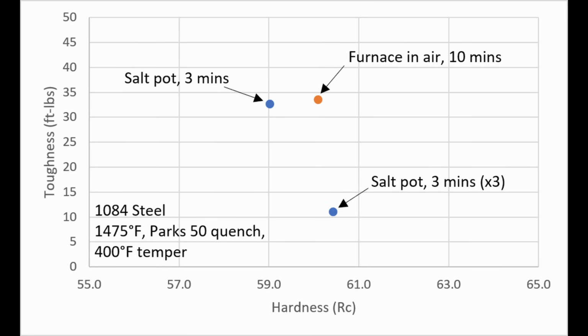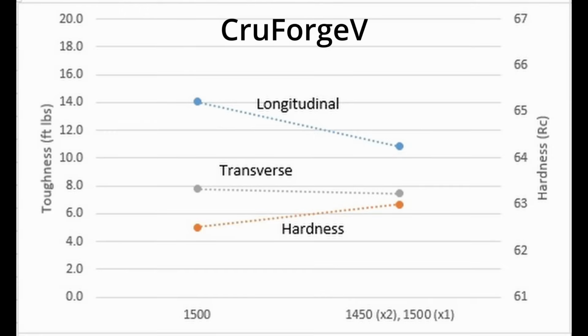But with a lot of testing that I've done, I'm not sure if we are getting grain refinement all the time. And if we are, there's not much difference between a fine grain and a little bit finer grain. And for a lot of these steels, the toughness is limited by other things like carbides, and refining the grain size a little bit doesn't make much of a difference. Nothing to get excited about anyway.